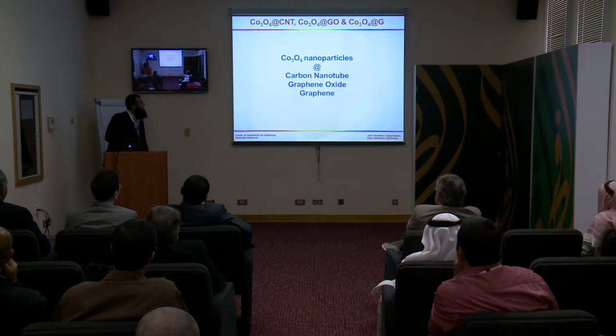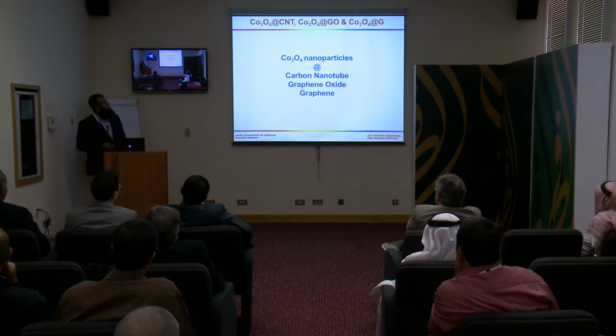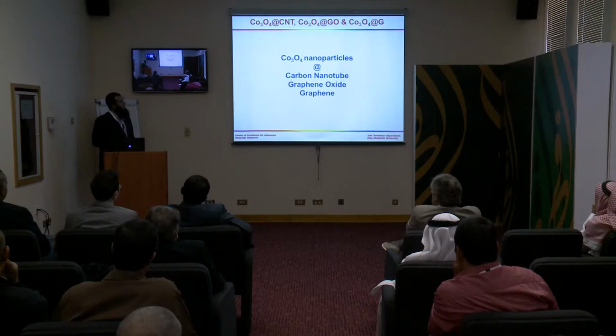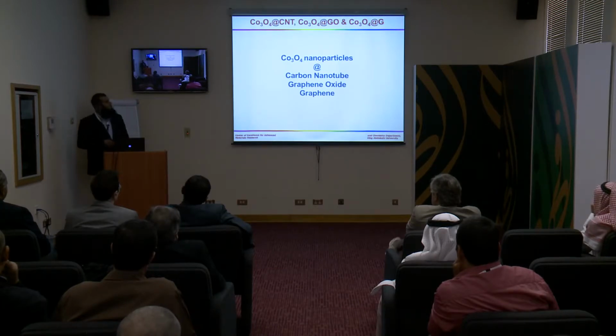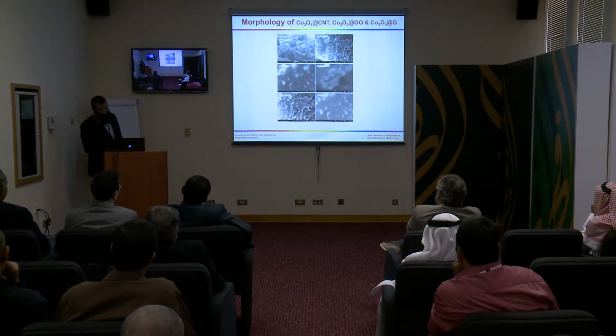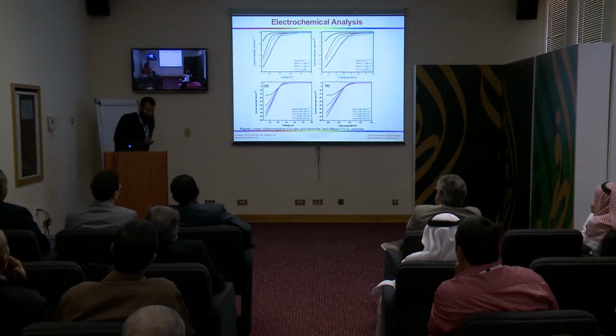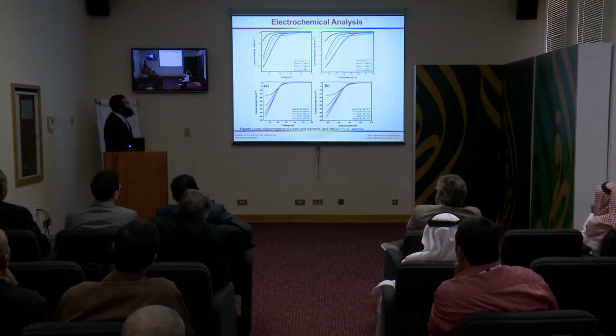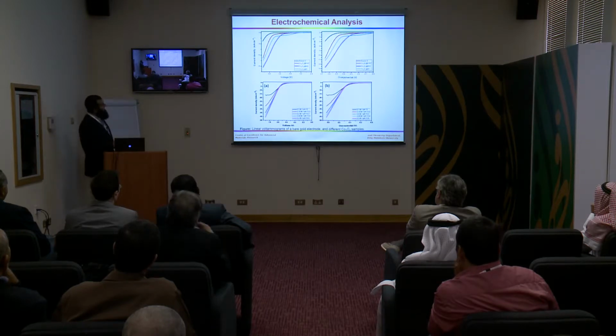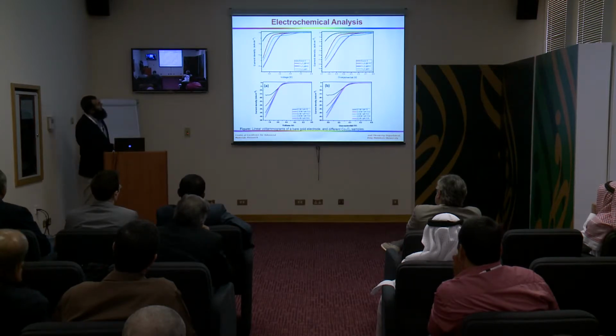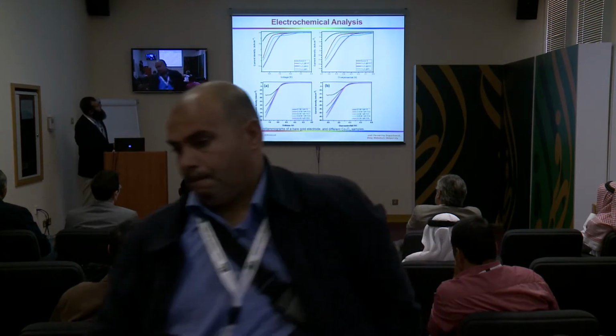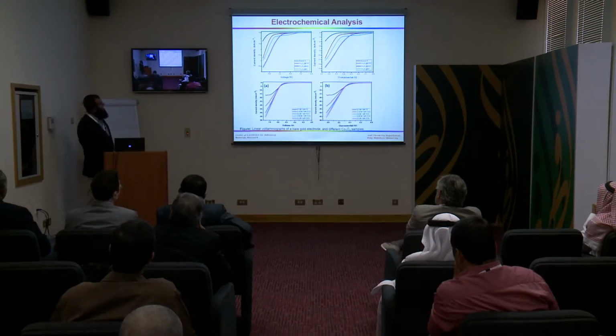Then we tried to grow the cobalt oxide on the surface of carbon nanotube, graphene oxide, and graphene, and we designed a material for water splitting. These are the images of the material we grew. When we studied the electrochemical property, you can see from the linear sweep voltammogram that the cobalt oxide grown on the surface of graphene oxide shows high current density and low overpotential as compared to the other materials.